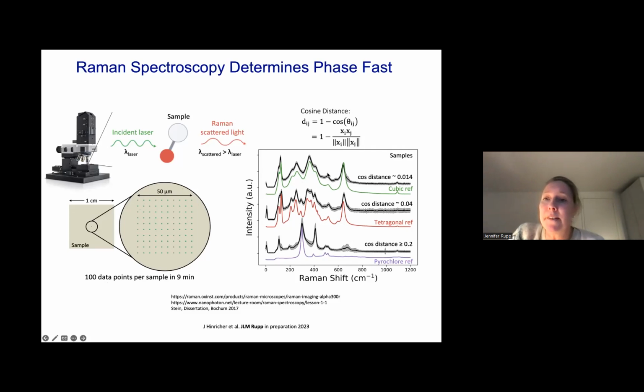And you can say, well, the ideal sample, for instance, for the cubic reference has to look like this. That would be one for the tetragonal and one for the pyrochlore. And we're trying to understand, like for mixed phases, how much is acceptable. And if you're 98% dense, how much will it affect the conductivity? And these boundaries are sometimes not as clear. So over years, this wasn't even published very strongly because people published the best one. But we have now to understand also the bad cases to really propose later where the boundaries are. They will change per material class for sure.